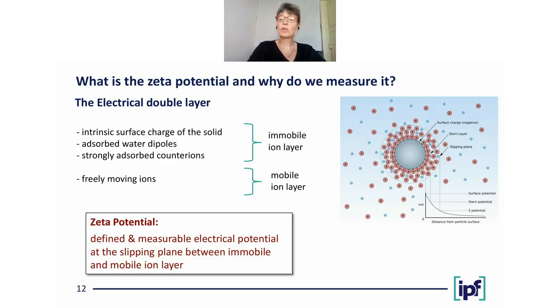And if you move the solution with respect to the solid surface, you get a slipping plane or shear plane between this immobile and the mobile ion layer. And the Zeta potential is the electrical potential exactly at this slipping plane between the immobile and the mobile layer. It is not the surface charge itself. The surface charge cannot be accessed, but the Zeta potential is kind of a measure of the surface charge.